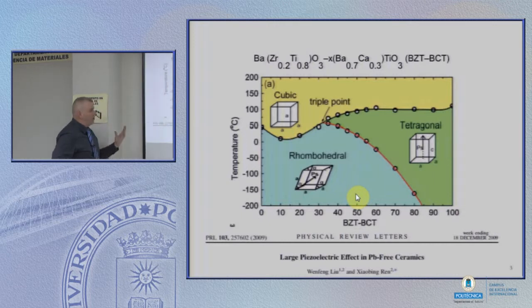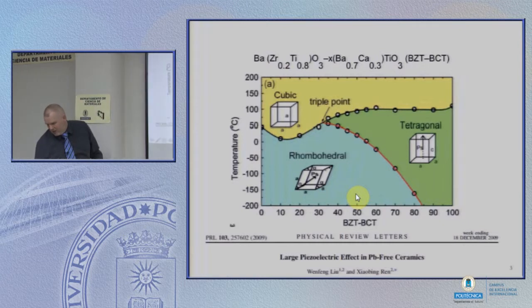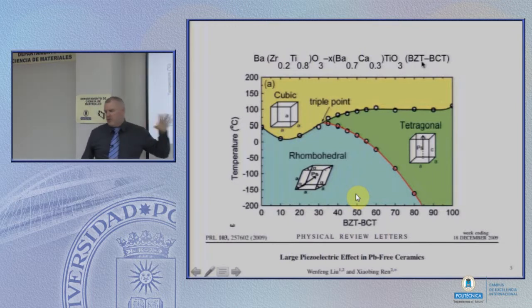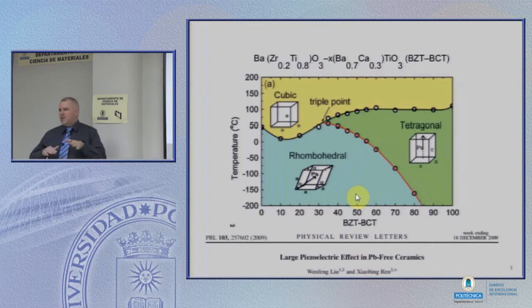So he had introduced essentially what you can see from the formula. If you look at the formula on the top, it's a material which consists of barium, zirconium, titanium oxide, essentially a modification of barium titanate, and barium calcium titanium oxide, nicknamed BZT-BCT, essentially an alloy system. What's amazing about the discovery is that people had worked on BZT-BCT materials in the 1950s, but they picked compositions all the way around the ones that perform well. Essentially, they did all the compositions around the ones that perform well.